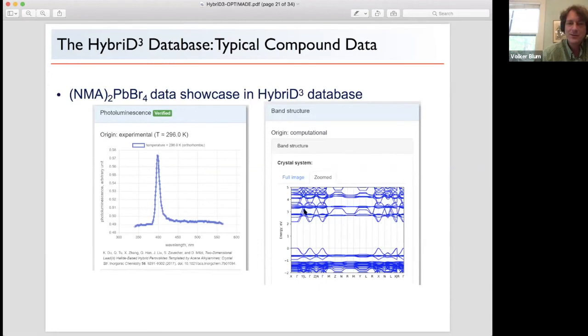And if you know what you're looking at, then you find that these are very dispersive bands at the band edges. And so this is actually a material with band edges contributed by the inorganic, and the organic basically acts as a spacer material with some dielectric function. So you can learn something from that. You can also download it. And this should be calculated at the level of hybrid density functional theory. So our other work indicates that there is some trustworthiness to the band alignments that we actually calculate.